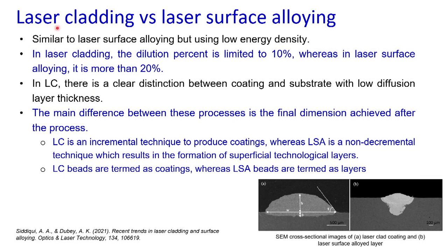Fine. Let us understand the difference between laser cladding and laser surface alloying. Similar to laser surface alloying, cladding is used to deposit materials over the substrate material, but the energy density is low. In cladding, the energy density is low. In laser cladding, the dilution percent is limited to 10%, whereas in surface alloying, it is more than 20%. So this is a very important difference between laser cladding and laser surface alloying. In laser cladding, there is a clear distinction between coating and substrate with low diffusion layer thickness.